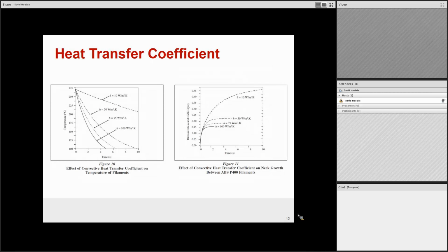Another factor that was tested was the heat transfer coefficient. They determined that the heat transfer coefficient has a very high effect on the dimensionless neck radius. So in order to maximize the strength between your parts, you actually want a lower convection coefficient. And the downside to this model is that there's no experimental data to back it up. This was done entirely with the lumped capacitance method, so take this with a grain of salt.